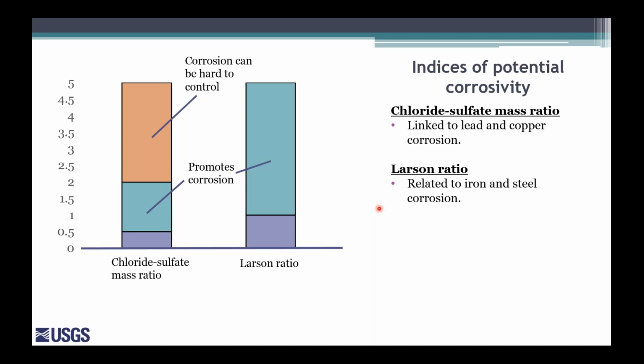And just so you have a sense of the magnitude that's considered to be important for these indicators, a chloride to sulfate mass ratio greater than 0.5 is thought to promote corrosion. And when it gets above 2, it can actually be difficult to control corrosion using traditional means within a water distribution system. On the other hand, the corrosion of iron and steel can be promoted when the Larson ratio is above 1.